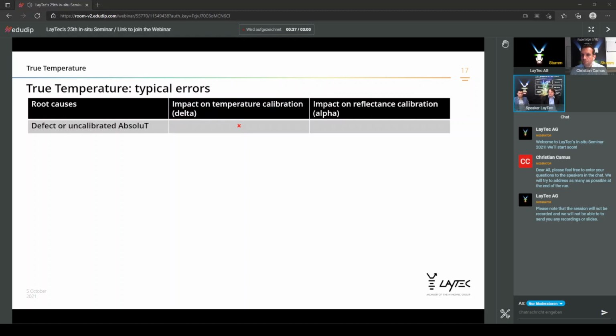So it's essentially important that you treat your absolute T carefully, always keep it in the safe container, and, more importantly, make sure that it's calibrated within the recommended calibration cycles as mentioned in the manual and in the paperwork of the absolute T. If you see any significant offset or inconsistency in the resulting delta or consistency of the true temperature when you do the true temperature or EpiTT calibration, even though the absolute T you are using was just recently calibrated or is even within the valid calibration period, then it's highly recommended to turn it back to LayTec to have it inspected or maybe even repaired.